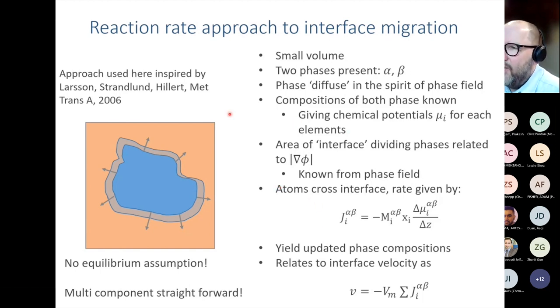And if that's part of the interface, we have two phases present, alpha and beta. And these phases are diffuse in the spirit of phase field. In the spirit of phase fields, this illustration here is actually not accurate, but for the sake of understanding, I assume that we have something like an arbitrarily shaped phase surrounded by a matrix. So we know the compositions of both phases, and if we know the compositions, we can calculate the chemical potentials.